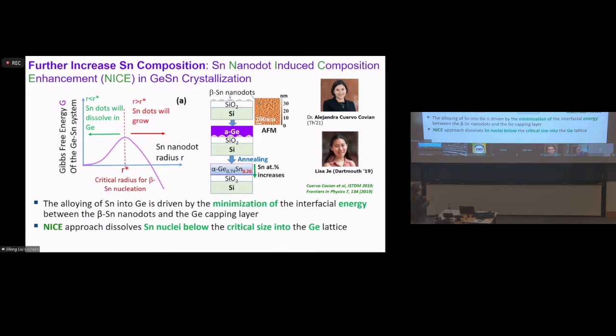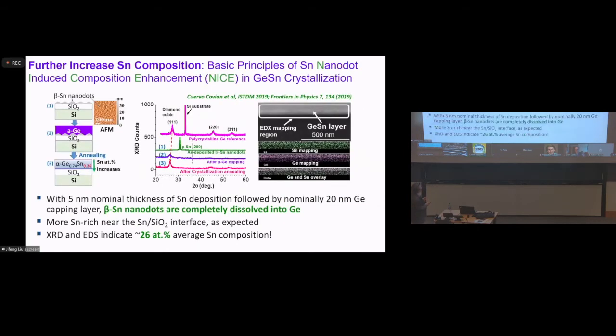This experimental work was done by Alejandra in collaboration with Lisa. Lisa was actually an honors thesis student at the time. And essentially, they found this to be true. If you look at the schematics, the first step is the tin deposition. We have an X-ray diffraction pattern showing very clear beta tin peaks, very well crystallized. You can tell the orientation.